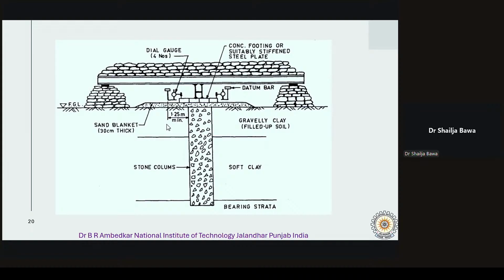Load settlement and time settlement relationships can be plotted from the settlements observed for each increment of the load. For example, we can take the reading at 1 minute, 2 minutes, 4 minutes, 8 minutes, 16 minutes, half hour, 1 hour, 1.5 hour, 2 hour, 3 hour, 4, and like that. Okay, and these intervals may be modified if you desire. And after taking the settlement at each time and each load, we can plot the graphs. So after increasing the load in at least 5 stages, the load test is continued for 10 to 12 mm settlement at design load for the single column test, and 25 to 30 mm settlement at the design load for a 3 column group test.